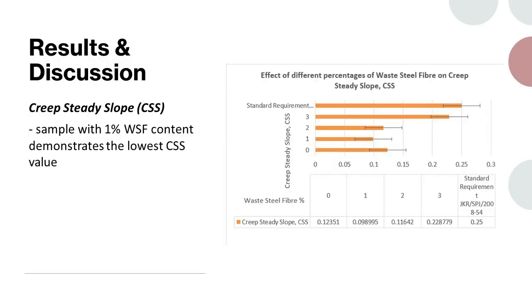Based on the CSS data value, it is proven that the sample with 1% WSF content demonstrates the lowest CSS value, indicating the highest resistance to rutting amongst the tested samples. This implies that the asphalt mixture with 1% WSF content is less susceptible to permanent deformation under load, making it more resilient against rutting. In summary, the data analysis highlights the impact of WSF content on the rutting resistance of the asphalt mixture. The sample with 1% WSF content exhibits the highest resistance to rutting, while higher WSF percentages, which are 2 and 3%, result in decreased resistance to permanent deformation.